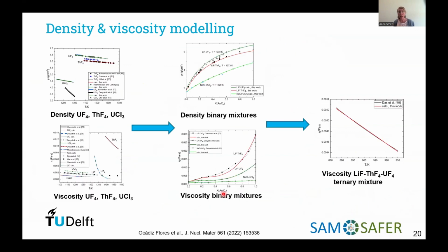We have done this, as I mentioned, for nuclear fuels. We have followed a CALPHAD type of approach where first we need to build models for the end members, models for density and viscosity of uranium tetrafluoride, thorium tetrafluoride, and uranium trichloride. Once this is done, we can move on to binary mixtures where we describe the density in a binary mixture. And finally, we can go to higher order systems until we get description of density and viscosity for a ternary mixture. In this example, lithium fluoride, thorium fluoride, and uranium tetrafluoride.